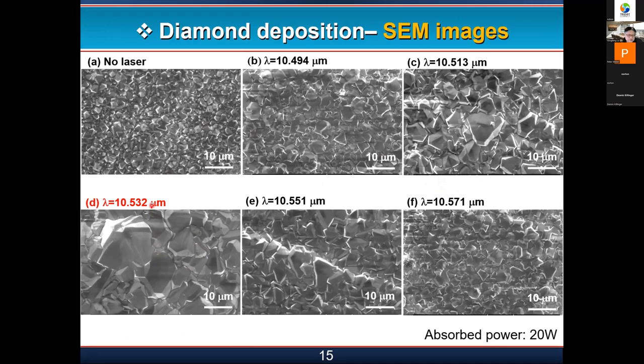And if we tune this wavelength slightly away from the resonance, you can see that both growth rate and crystallinity will drop quite a bit. We also control the same amount of energy being absorbed by the flame. So in terms of thermal energy, the energy pumped into the system is the same, but when you have different wavelengths, their effect is totally different.